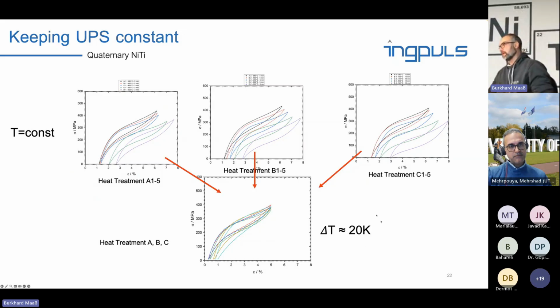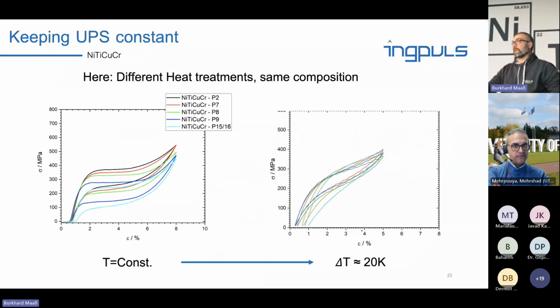This is just a delta T of 20 Kelvin, but the methodology, we will increase this so that we can get up to 50, 70, 100 Kelvin, and always having a next material phase kick in so that the machine always works with the same mechanical conditions under different temperatures. So here